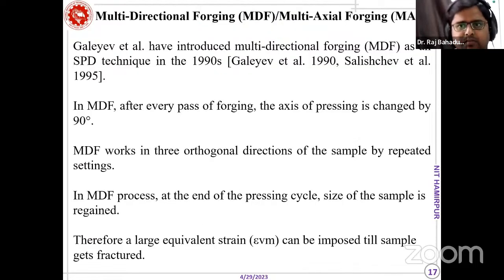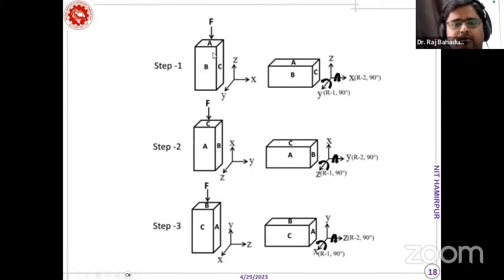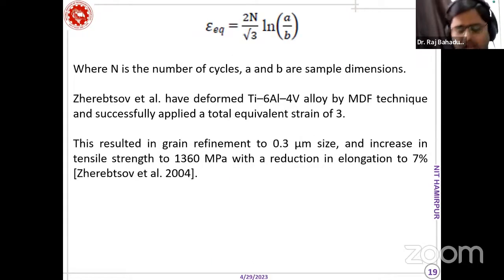And coming to multi-directional forging, again we can have the cross-sectional area intact after the end of the process. In step one, you rotate the sample in particular directions and keep on deforming by the forging process. At the end of the process, you will find a similar kind of cross-section, and at the same time we have imposed a lot of strain in the material. So microstructural features will be refined, and dislocation density will be increased like anything. The mechanical properties will be enhanced many times compared to the coarse grain material. I will discuss the mechanical properties also at the end.